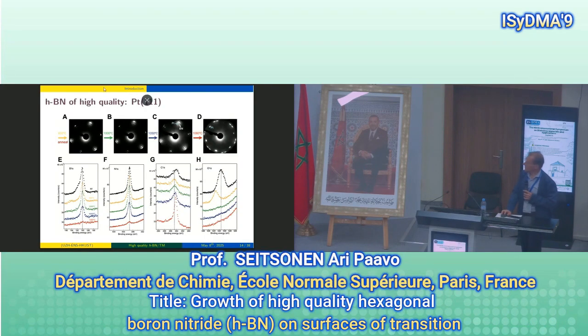And here then some experimental results. I have no time to go into details. Well, you see different structures. Again, this is the initial structure after the growth, and then different annealing temperatures. And this is the so-called LEED, which shows the periodicity in the reciprocal space. And the other probe I show, again, no time to go into details, but this is the X-ray photoelectron spectroscopy.